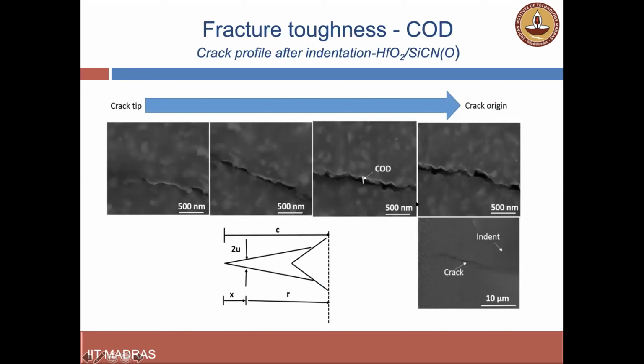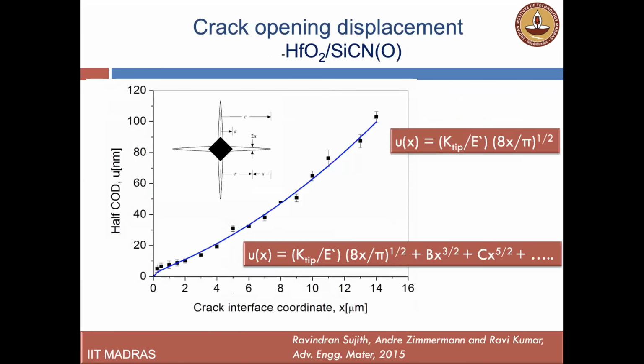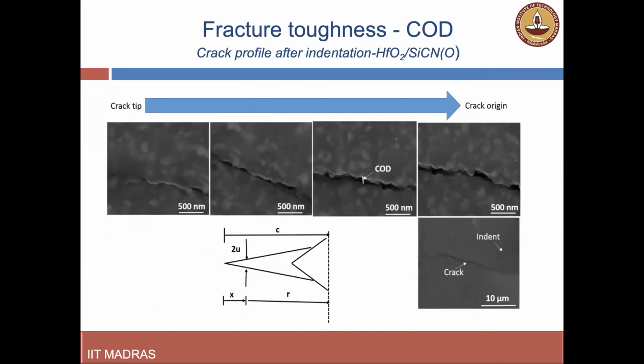And again, as engineers, we don't want these materials to fail. So we look at their fracture resistance. We calculate the fracture resistance from a very atomistic point of view. We call this crack opening displacement. It's a very time consuming effort.